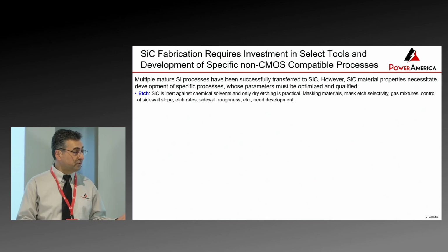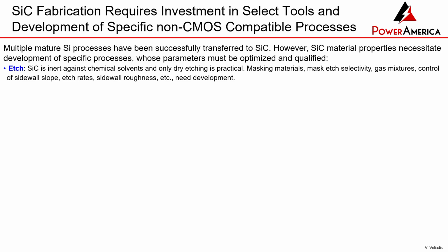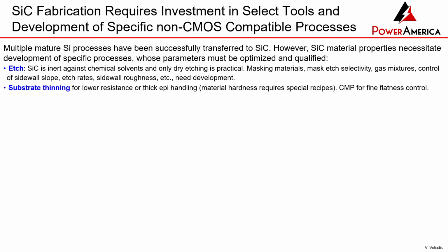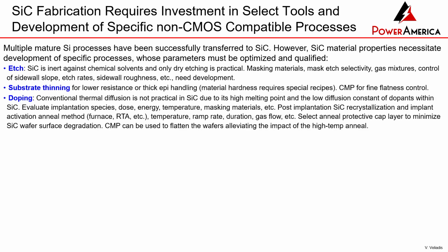You need to etch, right? It's a very hard material, so the resist mask will no longer be good. The selectivity is very bad, so you need a hard mask, and you need to develop that. The second thing is you need to thin the substrate, because at lower voltages, like 1200 volts and below, the substrate itself is the biggest contributor to resistance. Substrate first, then the channel resistance, and the drift layer that holds the high voltage comes third. So thinning the substrate, you need to find ways to do that.